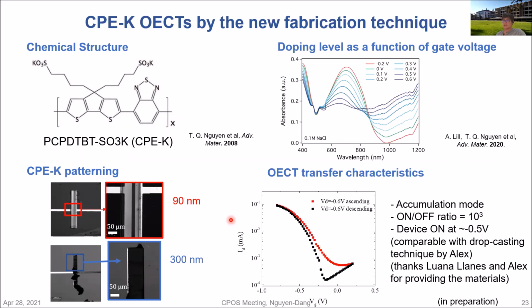I applied this technique with CPK. It's the new conjugated polyelectrolytes that are synthesized by the group, and here in this case by Luana. Alex Liu in our group has done a very good job of showing that this CPK can be an excellent active material for OECT. So I used the materials provided by Luana and applied the techniques, and I can pattern the CPK either with a thin film or with a very thick film. With thin film, we can have a very well-defined structure. With thick film, it's kind of difficult to remove some features. It also needs some more optimization work. But overall, the OECT performance of CPK OECT with the new fabrication technique is comparable with the drop casting technique done by Alex previously.